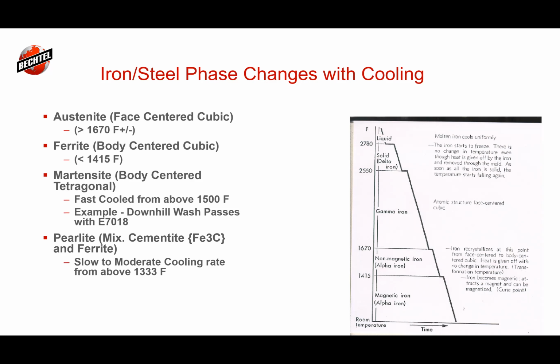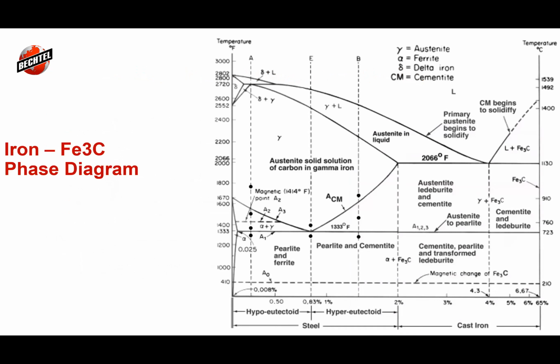If you only have 2 minutes to find somebody, you might not be in the same group you would find if you had 30 minutes to find your group. So austenite to ferrite is a phase change. And if you don't give it time to transfer from austenite to ferrite, it'll go from austenite to martensite. Okay, so even with an A36, we've got chemical alloys or chemical additions we're adding in to strengthen the material, and we have cooling that can change.